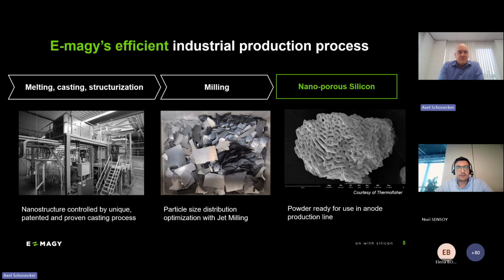In our case, we use a metallurgical silicon that is produced in Europe, for example, by companies like Ferroglobe or Elkem. So we have quite a good supply chain here in Europe. And what we do is we melt it again, and we crystallize it in a special technology with a rapid crystallization. And that allows us to produce these sort of flakes that you see on the middle picture. And in these flakes, there's a silicon nanostructure already built in. So the last step we do is we mill these flakes down to a porous silicon powder. And that is what you see in the right graph.